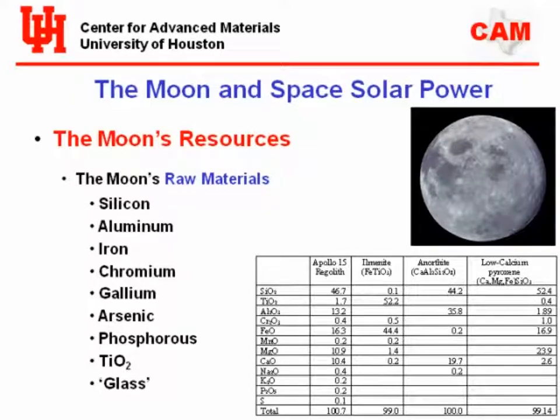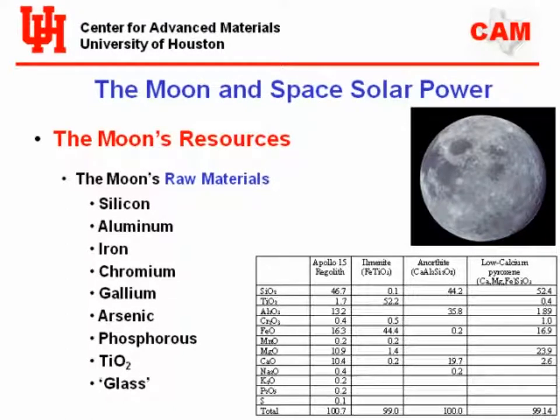What about the raw materials on the Moon? Apollo 15 regolith shows: silicon dioxide, titanium oxide, aluminum oxide, chrome oxide, iron oxide, manganese, magnesium, calcium, sodium — all the way down the line. There are a large number of oxides on the Moon, and these oxides have all the metals of technological interest. It's got silicon — great, because we can make solar cells out of silicon.